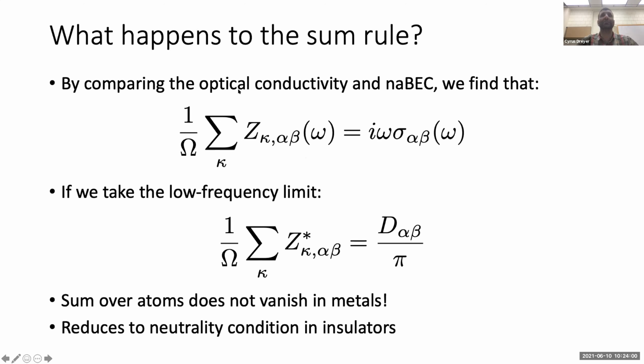I will give an argument about why this is the case. The more detailed argument is of course in the paper, but for now I'll just take this as the result. If we take the low frequency limit of both sides of this equation, then we get that the sublattice sum of the Born effective charges is exactly proportional to the Drude weight of the material.